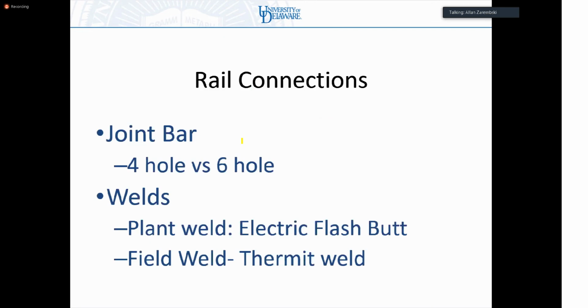Okay, so how do you connect rail? So rail is generally rolled in lengths of between 12 meters and 100 meters. It used to be that the standard rail length was 39 feet, which was a little bit under 13 meters, about 12 meters roughly. But as you saw from the movie, modern rail is rolled to longer lengths. The movie showed 108 meter long lengths of rail after rolling, but then you still have to connect them in the field. So you can connect rail either using joint bars, which is a mechanical connector, or you can connect them using welding.